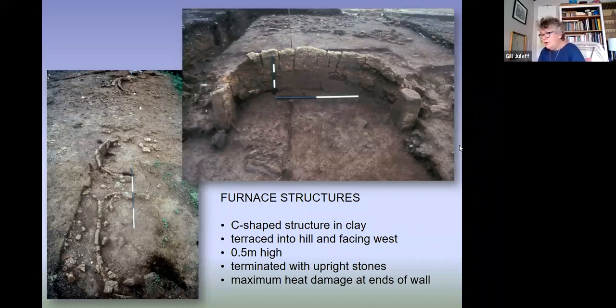This clay wall is terminated at either end with an upright stone. And the other thing that we consistently see is that the maximum heat damage to the clay occurs at either end of this wall, where it comes westwards and terminates with the upright stone. So we have this set of characteristics that repeated over and over again for these furnaces.